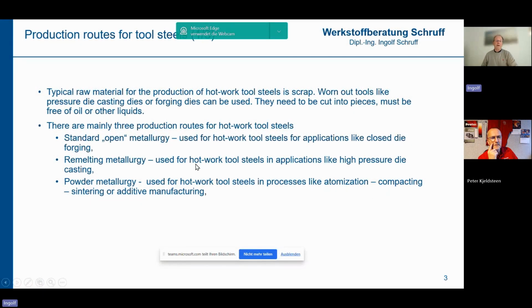And so we have generally 3 routes, and maybe I can show again. Yes, we have more or less 3 routes. The so-called standard or open metallurgy, which in case of hot work tool steels is used for applications like die forging. Remelting metallurgy, which in most cases is electro slag remelting, but can also be vacuum arc remelting, and that is mainly used for hot work tool steels in applications like high pressure die casting, but we also find it in some applications like extrusion or some plastic molding applications where we need extreme high purity and very good homogeneity.